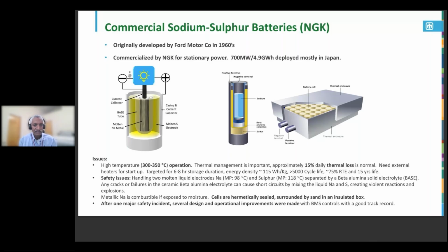There are some safety issues with these batteries because you're handling two molten liquids. If there are any cracks or defects in the beta alumina ceramic tube, these two molten liquids can mix and then create explosions. Metallic sodium is combustible if it is exposed to moisture. Typically, these batteries are hermetically sealed and they are surrounded by sand in an insulating box. The box that is shown there, they make it like 5 kilowatt hour modules with several cells combined in series and parallel to get the required power output.